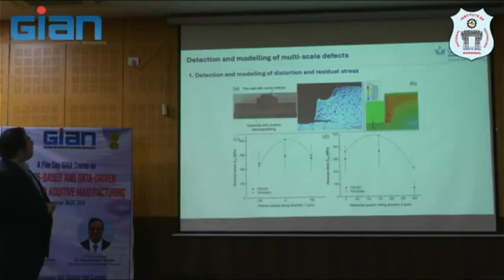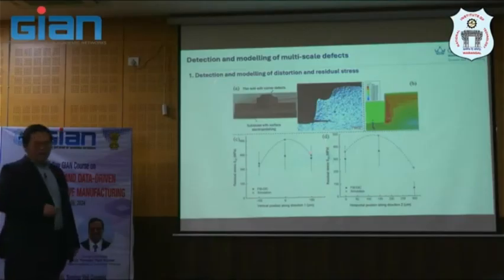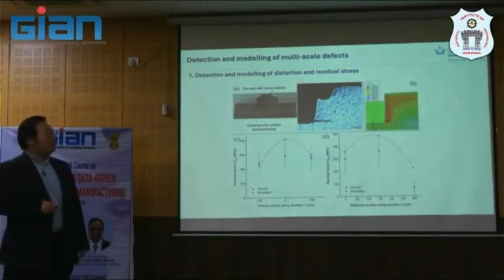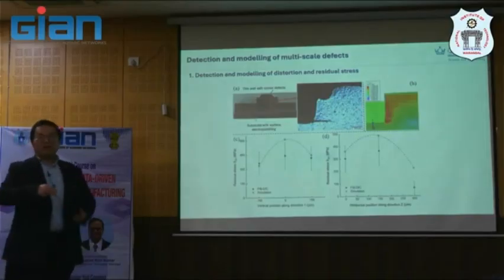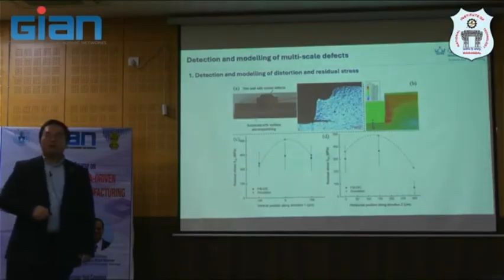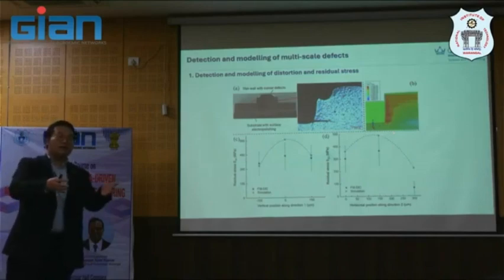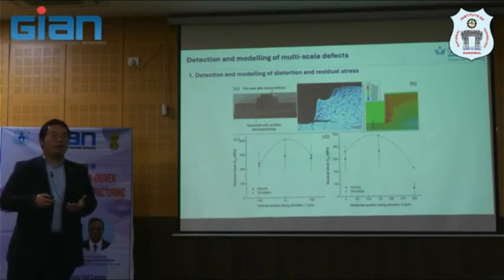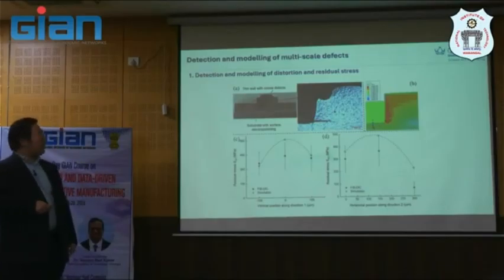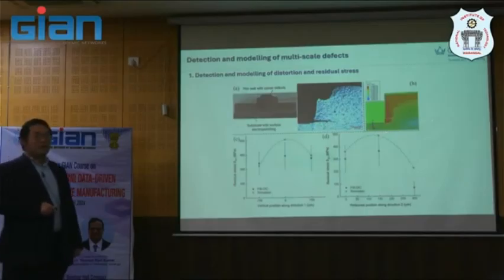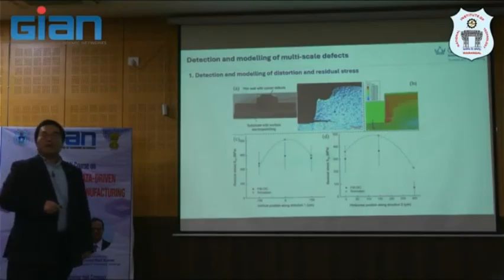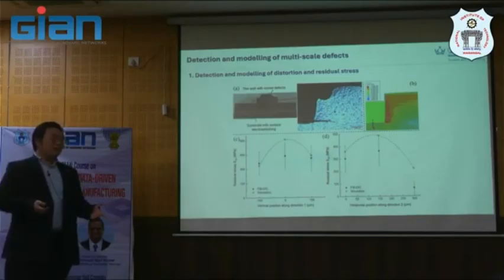So the defect here, you see detection of this distortion actually is not easy, and this is related to length scale. This is a large length scale, component length scale. It's related to solid mechanics. It's related to mechanical engineers like yourself to help simulate it at the part scale. But actually, using homogenization that does not contain microstructure information may not correctly capture what happened during the 3D printing, because the case in 3D printing is not homogeneous across the structure.